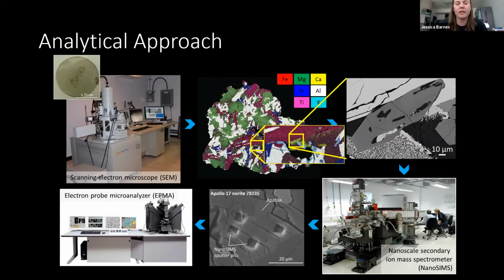What I'm looking for primarily are the chlorine hosts, so I'm most interested in apatite, which usually comes out in these yellow minerals, indicated by the calcium hotspots. Then I'll go in and do some detailed imaging using backscattered electron imaging and also secondary electron imaging. Both are really important. Backscattered electron imaging is really useful for getting an idea of the surrounding mineralogy, but also to look for any zonations. You can see some zonations in this apatite here. And secondary electron imaging is really good to understand the surface topography and the presence of cracks and fractures throughout the apatites.